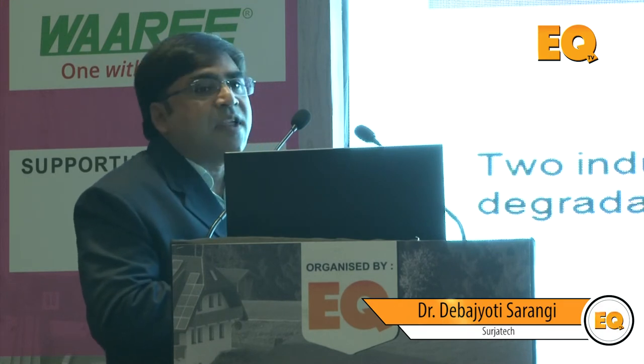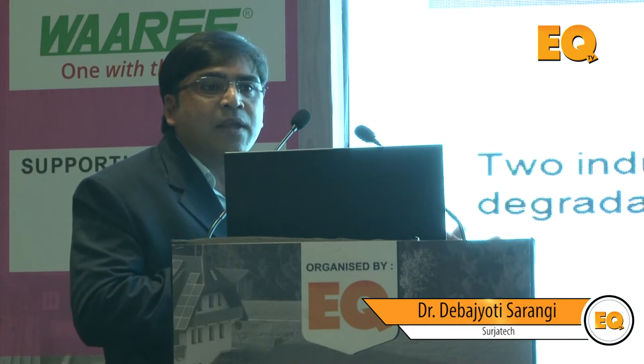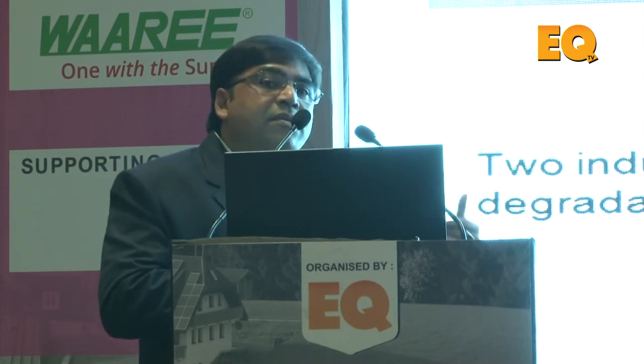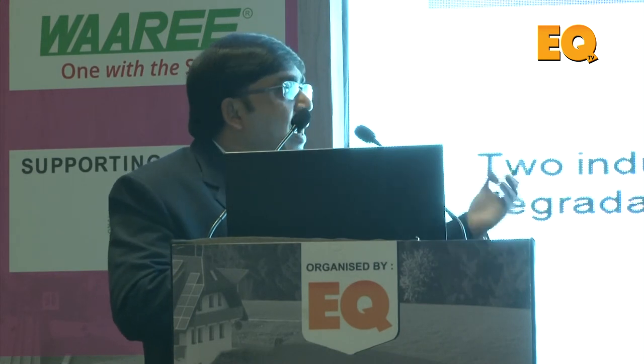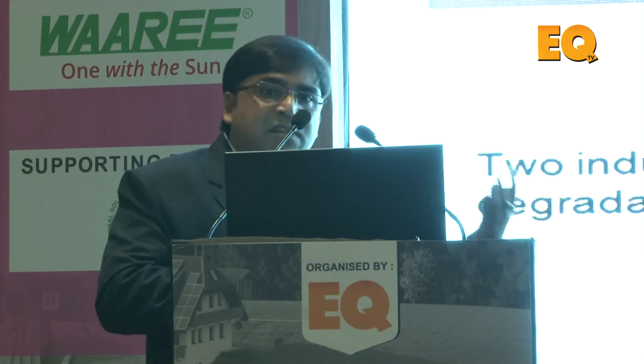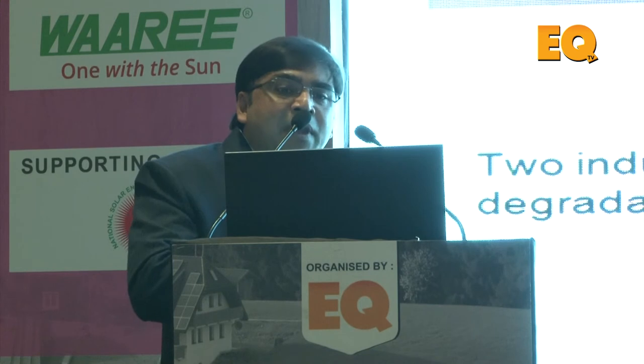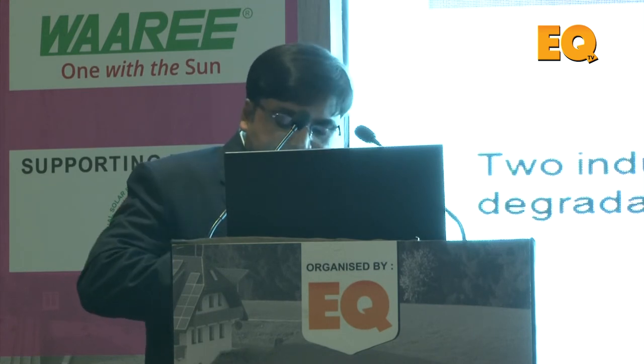One of the problems is that EVA is getting yellowing with time. As I told, the moment it's getting yellow, you will be losing your power. So you need to try to select other kinds of materials, the EVA-free material. This is one of them. Then the Borealis, some kind of polyolefin-based materials. So there is no ethyl, so that can really avoid this 10% reduction.